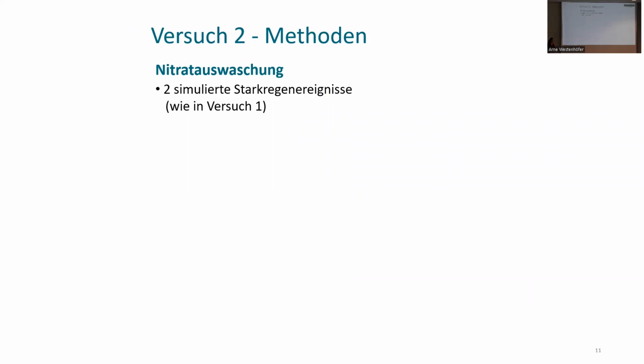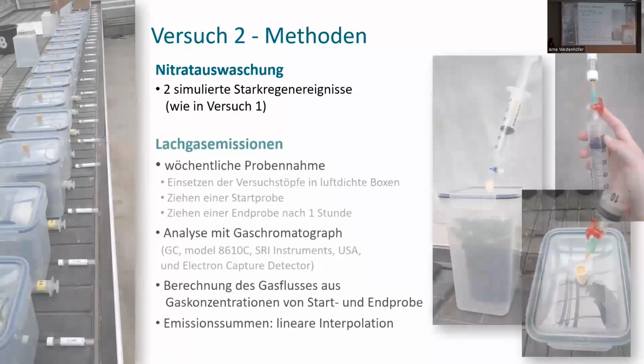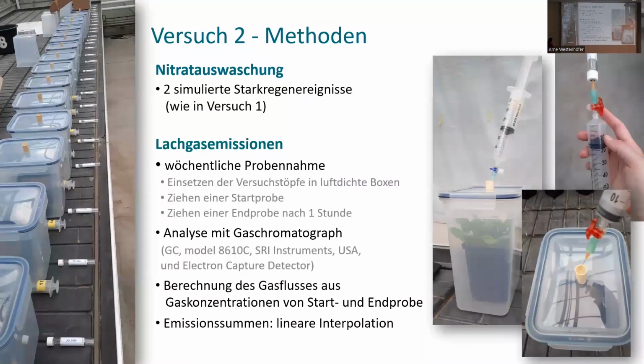Here again, we have simulated two heavy rainfall events, one right before sowing the spinach to leach out as much of the nitrate as possible, and the second event after harvesting the spinach. In addition to that, we have measured the nitrous oxide emissions. This seems complicated at first glance. It's not that complicated anymore. We had airproof boxes where we put the product in, and we took a gas sample and analyzed it with a gas chromatograph. And we had an initial and an end sample after 1 hour, and we could measure the greenhouse gases that were emitted from the soil in that time.